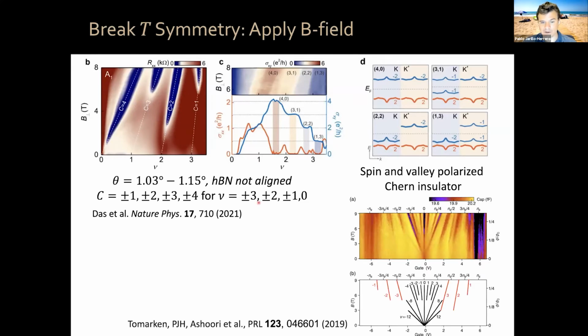More recently, and by the way, sorry, I should mention that together with my collaborator, Ray Ashoori, we had published earlier this paper where we measure the quantum capacitance of magic angle twisted bilayer graphene devices, not aligned to hBN, okay? And we saw this sequence of what we know now are Chern insulator states with slopes of Chern numbers of 1, 2, 3 at filling factors 3, 2, 1, etc. Okay. Back then, we identified the host of the butterfly physics of the system, but not the nature of Chern insulator nature. So that was an oversight. We should have spoken to more theorists about this, and we didn't realize it. But it was already present, those Chern insulators in this data clearly.